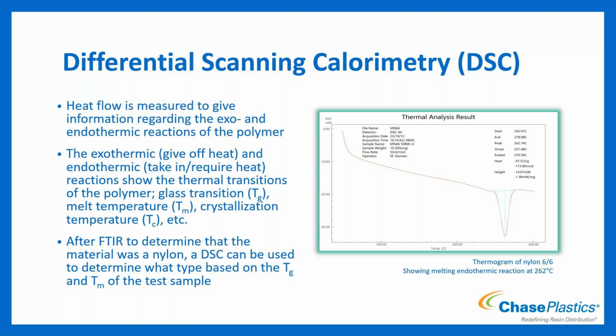So a great use of this would be after we've done FTIR, we know that it's nylon. We can turn around and do a DSC to determine what nylon it is based on its TG or TM, depending on which part you do. Most of the time you use the TM for it. But knowing that a 4,6, a 6,6, a 6, a nylon 12 are all going to have different melting temperatures, we're able to then go, FTIR told me it was nylon, DSC now tells me what type of nylon.